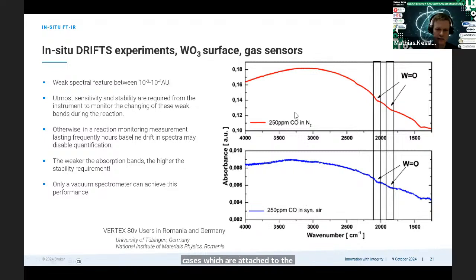And you see that if you use CO, we can really see two additional bands occurring here. This is only possible to see if we use an FTIR spectrometer with a very high sensitivity in this region. And again, we use a vacuum spectrometer for such observations.